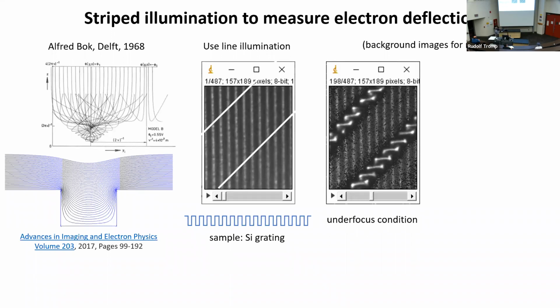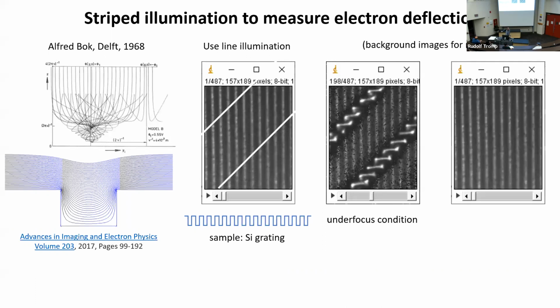And what we see is that as we approach very closely, the returned image, and I just keep the background image lit up for reference so you can see what it is. You see that the electrons now get deflected very strongly. We know exactly where they came in because we know the position along the slit, right? But we see this very strong deflection, which is just this deflection that Alfred Bok calculated in 1968.